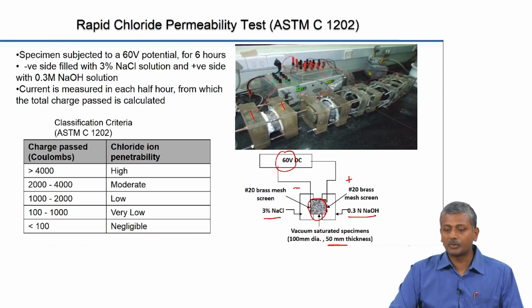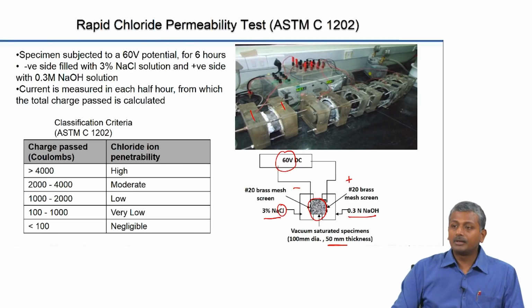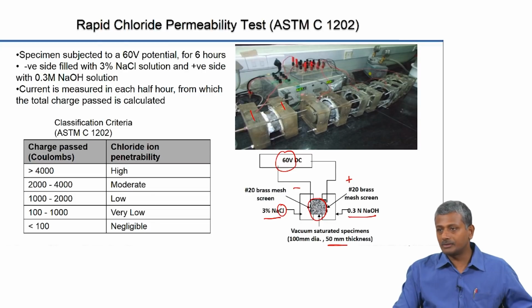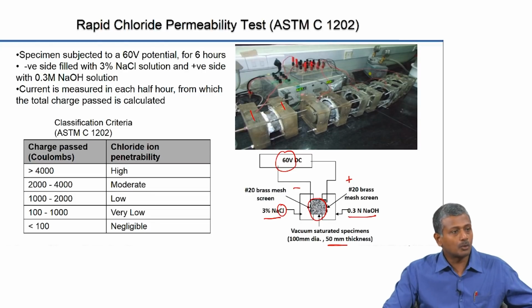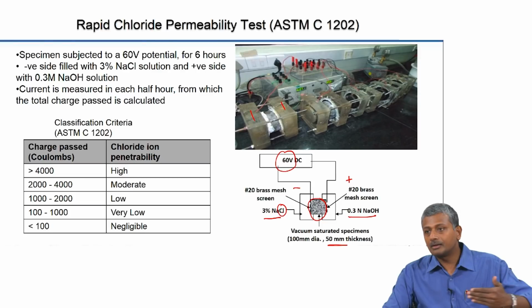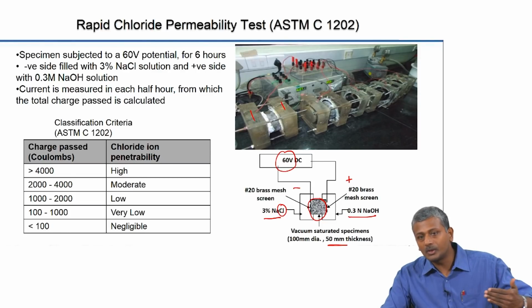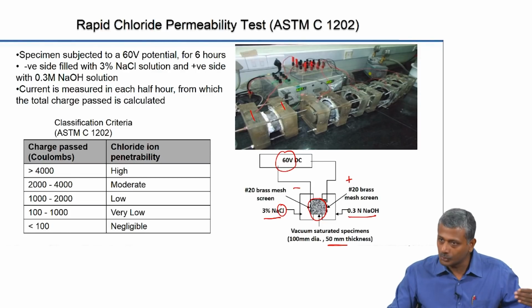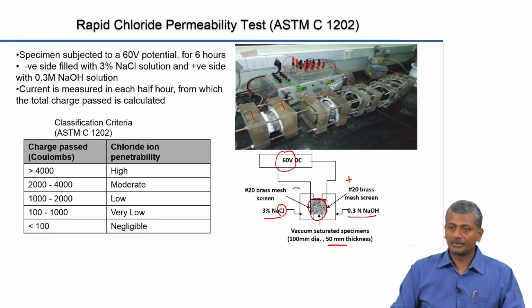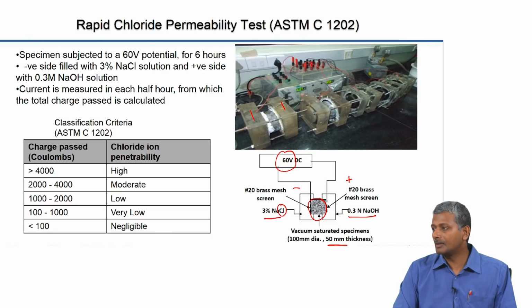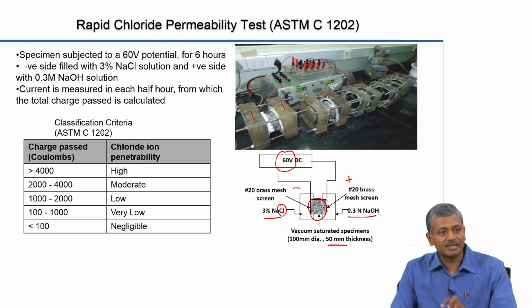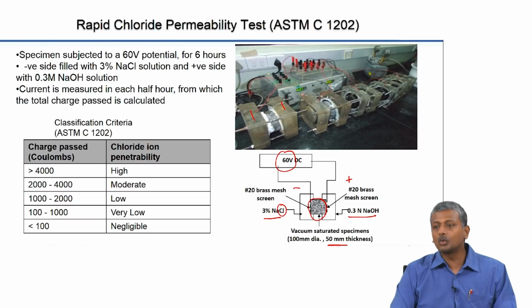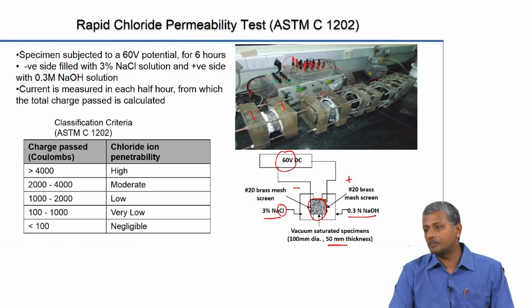So when you apply this potential difference, as I showed you earlier, the main purpose is to drive the chlorides from the negative cathodic end towards the anodic end, and this happens through the concrete, okay. But reality is that there are other ionic species also that are within the system that are going to be moving around, okay. So because of that, the result that you actually measure may not be truly indicative of the resistance to chloride ion penetration.